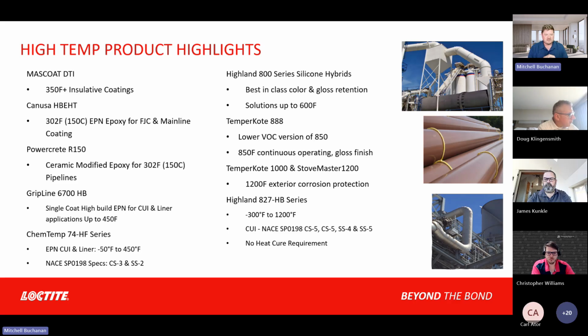When we look at the pipeline industry, right, most transmission pipelines are going to be below 100 C. There are some that are going to be in the 125 up to 150 C. So Canusa HBE-HT or Powercrete R150 for your ceramic modified epoxies. These are going to be high temperature pipeline coatings for AROs. Into the chemical containment and CUI coatings, you have the single coat, high build, Gripline 6700 HB, great for hot caustic service, up to 20 mils in a single coat. And so can save yourself a lot of money in processing if that's all the amount of temperature you need.